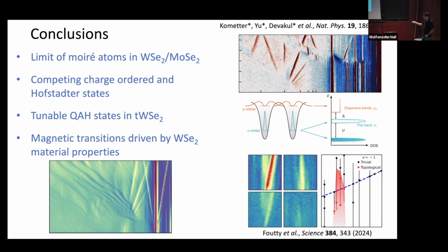And I'm not sure how generic to make this. This is all in a relatively low twist angle limit, what I've shown you so far, but at least in the low twist angle limit, the tungsten diselenide material itself seems to be strongly enough interacting that it is really dictating when you get different symmetry broken phases, at least as much as the Moiré physics is itself. So I think I'll end there, and I'd be happy to take any questions.